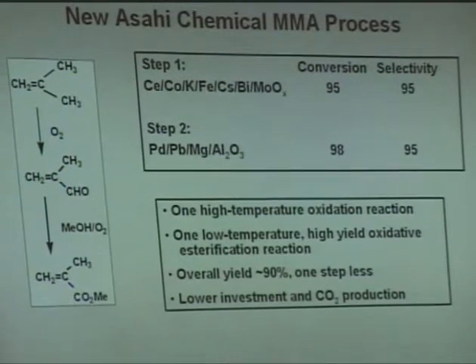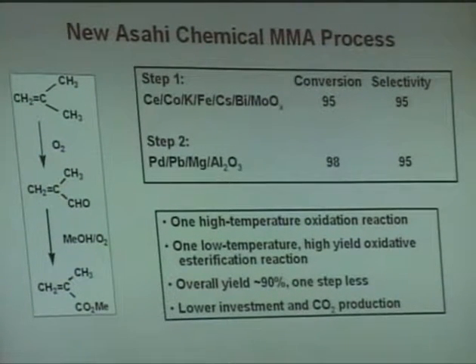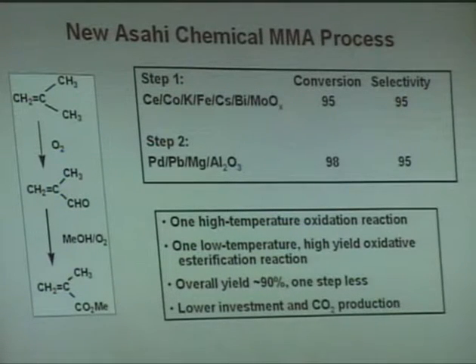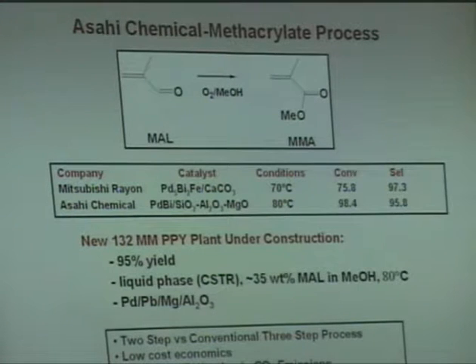Now the idea, they got a little bit out of the box there and said, okay, we really don't want to make methacrylic acid, we want to make the ester. So let's do an oxidative esterification. So they were totally able to eliminate that second high investment, high gas phase process, and they've dropped down to a liquid phase, low temperature, oxidative esterification to take the aldehyde to the ester with methanol and oxygen directly. Okay, big advance in this technology. So they do the conventional synthesis of methacrolein, do the oxidative esterification to methyl methacrylate.